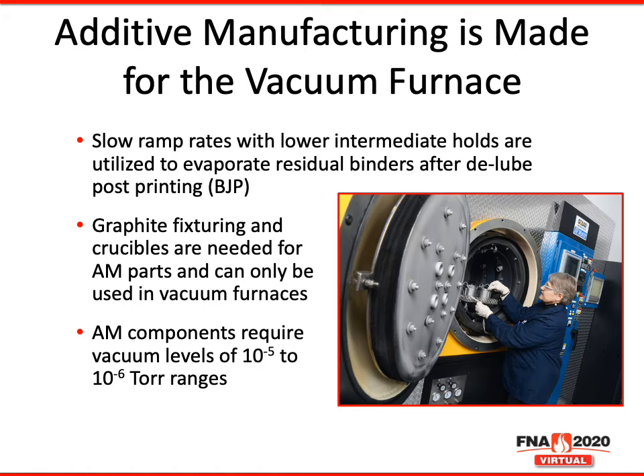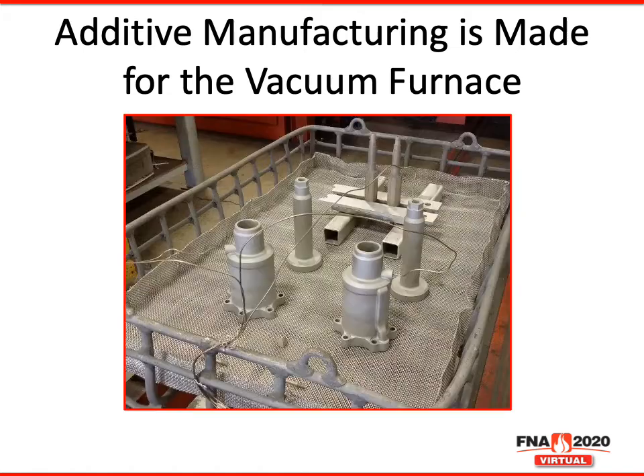So let's talk about additive manufacturing in the vacuum furnace. Slow ramp rates with lower intermediate holds are utilized to evaporate residual binders after the debind, or post-printing, of the BJP process. Graphite fixturing and crucibles are needed for additive manufacturing parts and can only be used in the vacuum furnace. Additive manufacturing components require vacuum levels of 10 to the minus 5 to 10 to the minus 6 torr range. This particular picture shows some 300 series stainless steel parts. Note where the thermocouples are in the parts and not in the base plate. So measurement of the part temperature is very crucial.